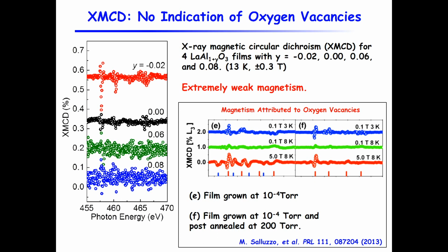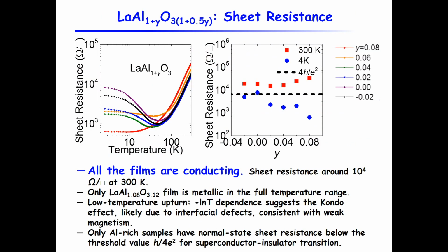This is the result of X-ray magnetic circular dichroism. Again, this is from the same paper in the literature. They have shown that if you grow it at low oxygen pressure, you'll see this kind of signal. When they anneal it at high oxygen pressure, the signal becomes weaker. That is from our data, so you can compare these scales. All our samples show a much weaker magnetic signature, which we believe indicates that we have much lower oxygen vacancies. It's not zero, so there are probably still some defects or oxygen vacancies, but it's much weaker than when you grow at low oxygen pressure.